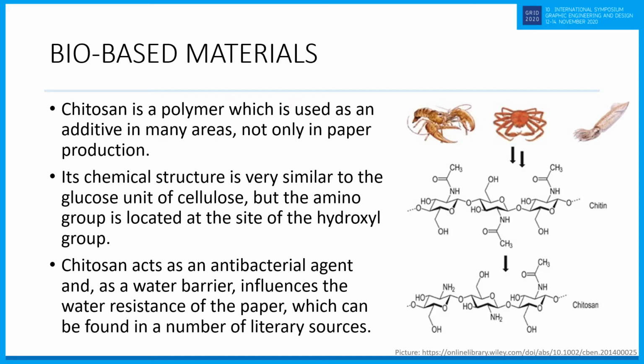The good and positive properties of chitosan are that it acts as an antibacterial agent, has good water barrier properties, and influences the water resistance of the paper if we use it as a paper coating, which can be found in a number of different research sources. Namely, chitosan is very poorly soluble in water. It achieves water resistance by combining its amino groups with hydroxyl groups of cellulose, thereby forming strong hydrogen bonds, which prevents water from binding into the cellulose molecules.